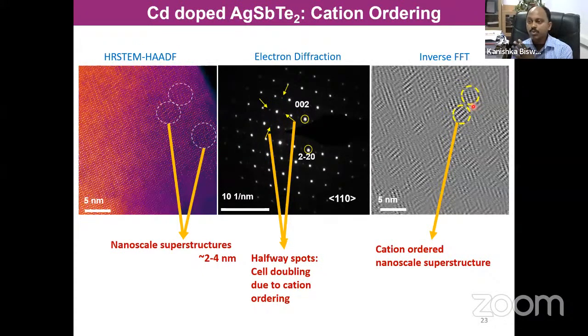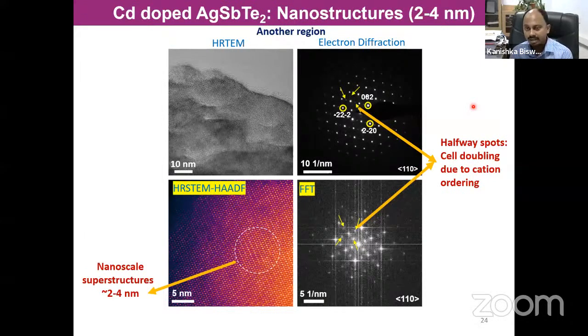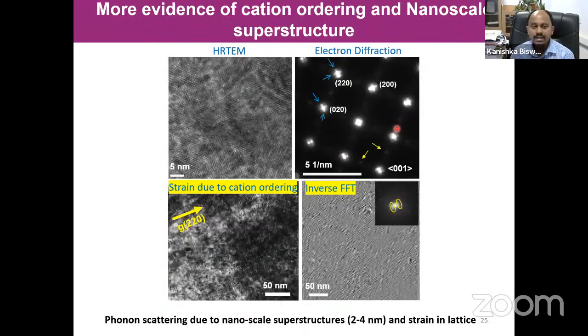So we have two handles in this compound. By doping cadmium, it orders the atoms in a domain size of 2 to 4 nanometer, which is exactly the size of the phonon, which is the message I wanted to give you. So then we keep on doing more TEM analysis. You can see these ordered domains and more electron diffraction. I'm not going to bore you more with this.